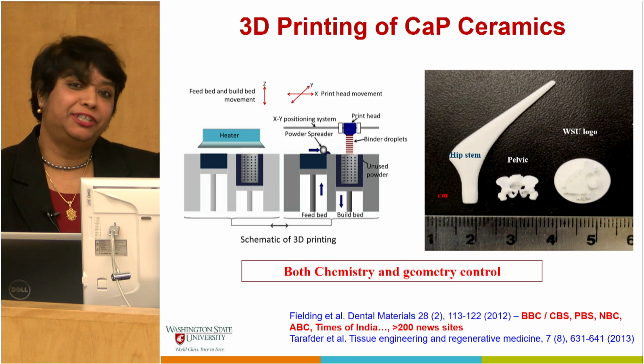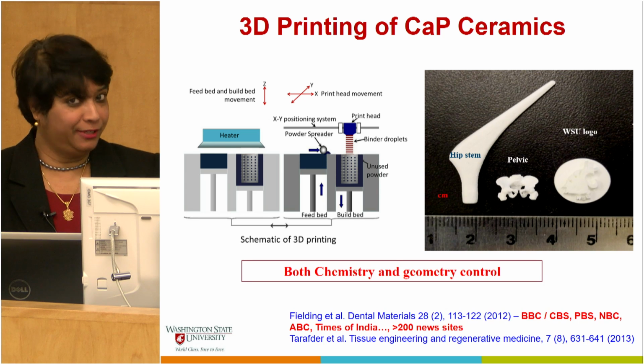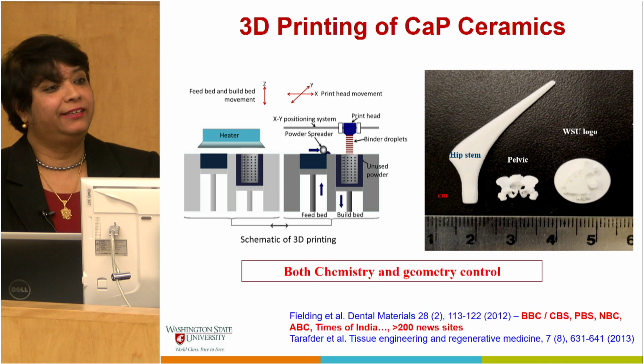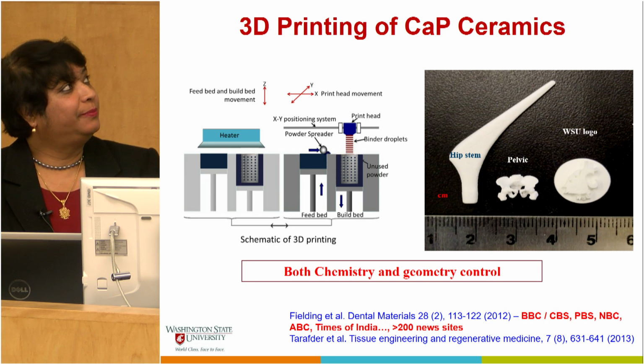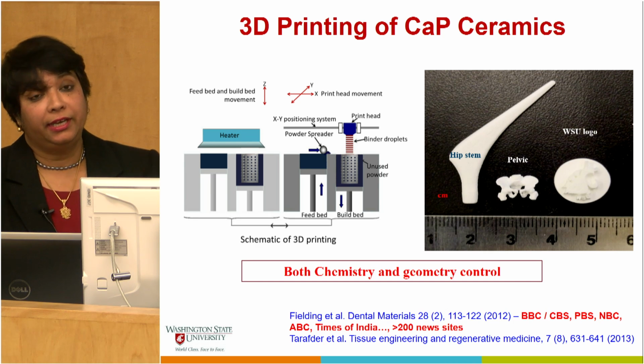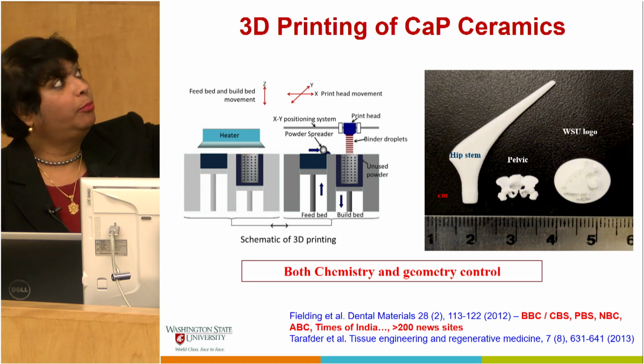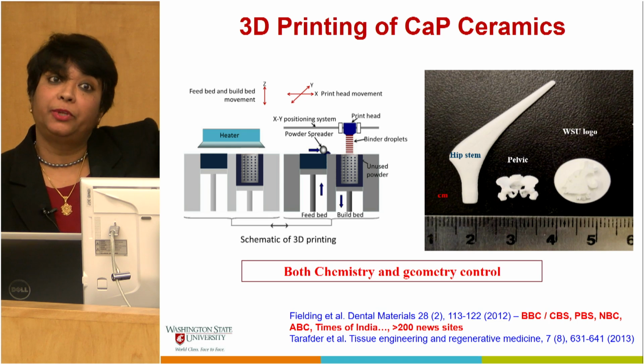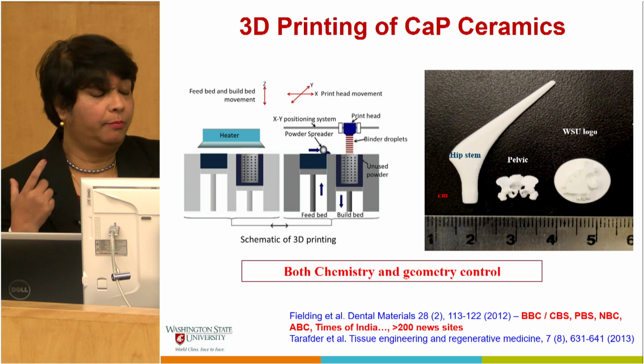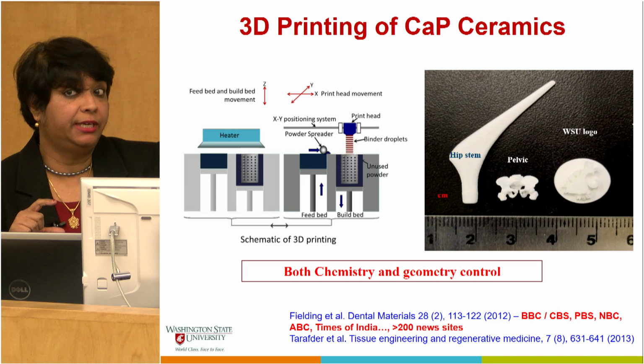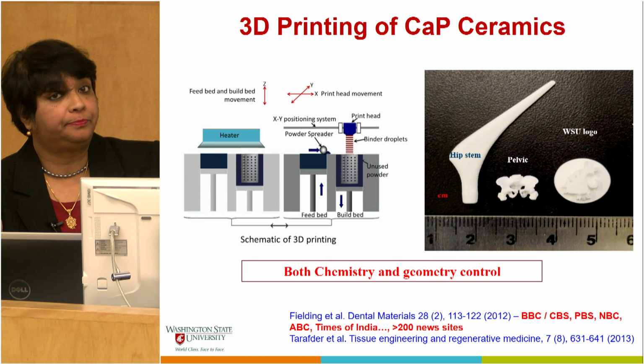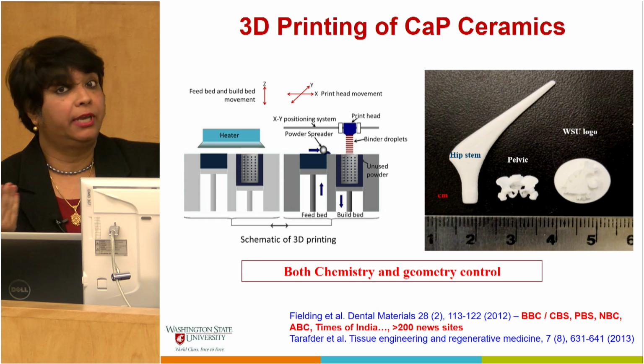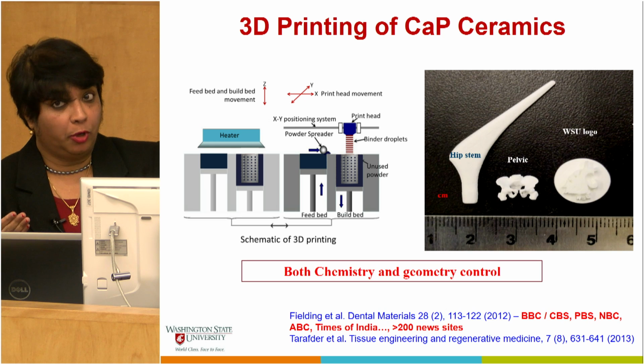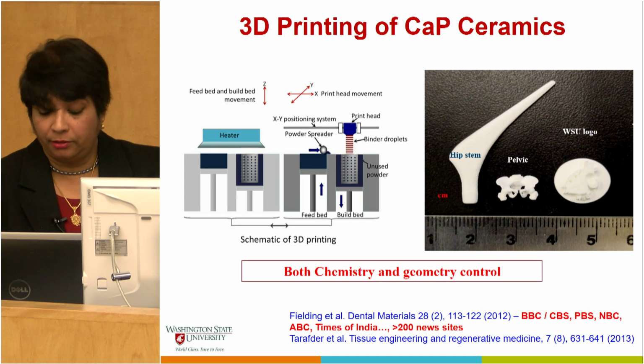I have a very traditional type of presentation today. I do not have any video. What you are looking at on the left hand side is, in our lab, this particular machine, a ceramic 3D printer. It uses a powder bed process which goes in the Z direction, and on the top, as you see, is the polymer binder nozzle which moves in the XY direction. The part is being made within the calcium phosphate powder bed based on the drawing that you have on the computer. Once it is built, you take it out, dry it, get rid of that polymer binder, and densify the ceramic part to get the strength. That's how we made those parts.